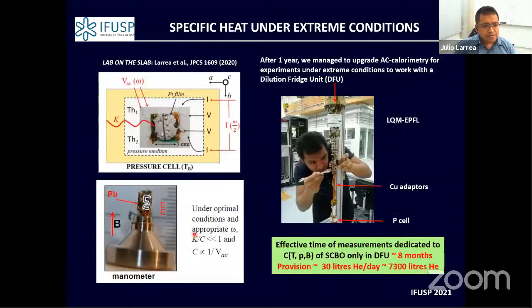So in this case, we try to approach the measurement of heat capacity from a different perspective. Instead of putting the sample on a calorimeter, we put the calorimeter on the sample. This is what we call, to give it a baptism, 'lab on the slab.' It consists basically of a sputtered heater, a thin film of 20 nanometers, a platinum film, on the sample.